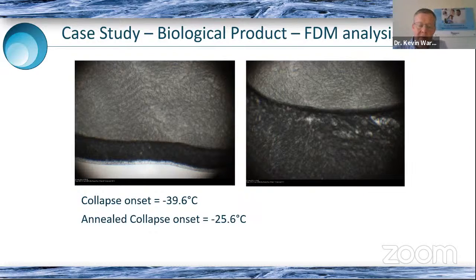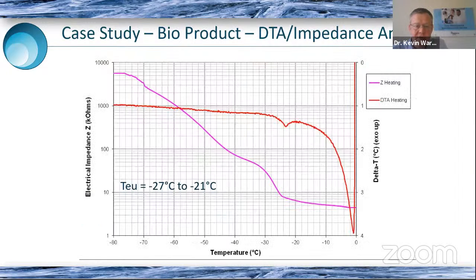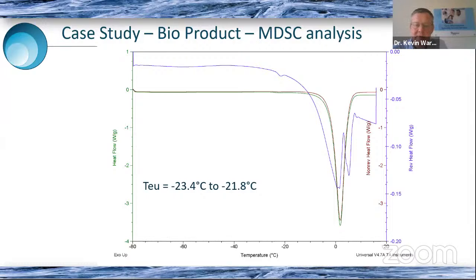Now, as a rule of thumb, if you have something which is, say, 10 degrees higher in collapse temperature, then generally speaking, you should be able to roughly double the freeze-drying speed, the speed of sublimation or primary drying. We carried out impedance analysis, which also suggested that once the material had been annealed, it had a eutectic melt that was somewhere just above -27 and finishing at -21. Actually, there was sodium chloride in this formulation, so perhaps it wasn't a huge surprise, but maybe without annealing, the sodium chloride was finding it difficult to crystallize. Just confirming that with DSC, here we saw a eutectic at -23. As you can see in the blue trace here, we've got this slight dip in the line just below -20. So that confirmed what we'd seen.